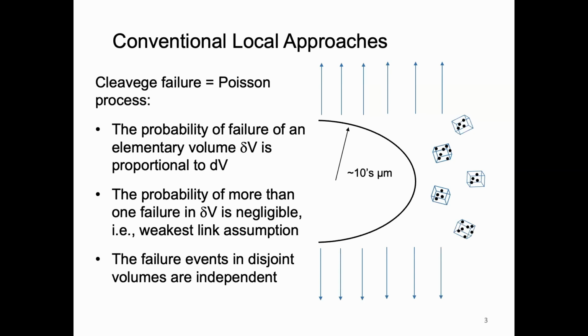The conventional local approaches for cleavage fracture start with the assumption that cleavage fracture is a Poisson process, which means these three things. The probability of failure of an elementary volume is proportional to the volume. The second thing is that the probability of more than one failure in one elementary volume is taken to be zero, which is the weakest link assumption. And the third one is that the failure events in disjoint volumes are statistically independent. So when you take these three assumptions of the Poisson process, you build all the local approaches to cleavage fracture.